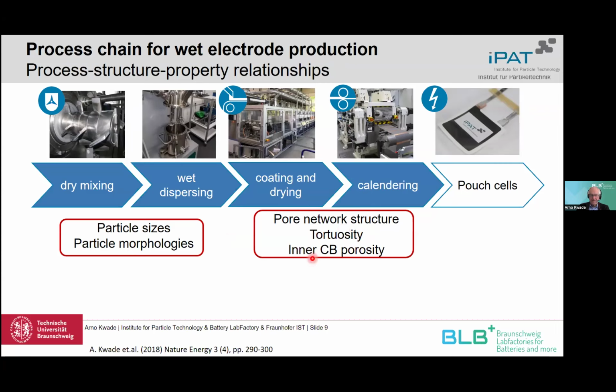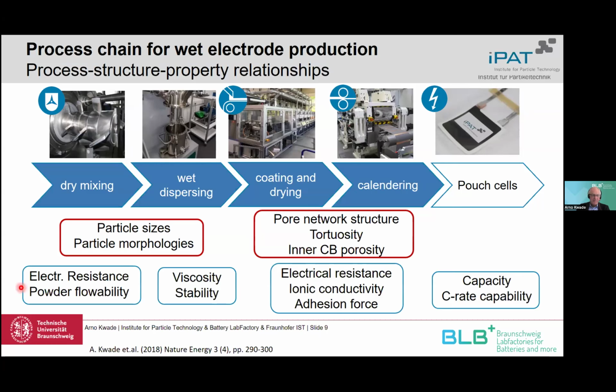And for example, we also determine the inner carbon black porosity as an important parameter for the structure. By that, you can then come to performance parameters. That means electrical resistance, powder flowability, maybe for the intermediate powder. We can have the viscosity and stability of our suspension. This is more for handling powder in suspension. And then we come to the electrode properties like electrical and ionic conductivity, adhesion force, especially also for handling the electrodes during further production. And then at the end to the capacity, C-rate capability, fast charging capability, etc.